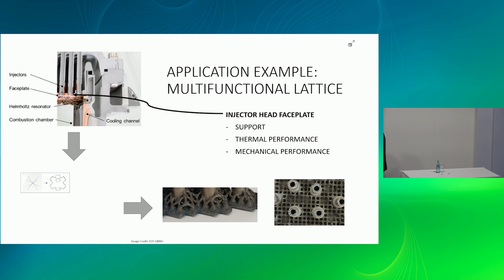We just printed some slices out of the injector so we could access it. By the strut thickness of those beams, the angles and the distribution around the faceplate, we could actually adapt the faceplate in a thermal way so that the heat is flowing very conformally through the faceplate. And for mechanical, we could distribute the stress very evenly over the faceplate. That overall leads to a longer lifetime of the engine. It's just ignited 30 times maximum. So it's actually a low cycle fatigue case that we have here. It does not have to stand a lot of cycles, but very high load cases for a very short time. And that's what that lattice structure is highly contributing to.